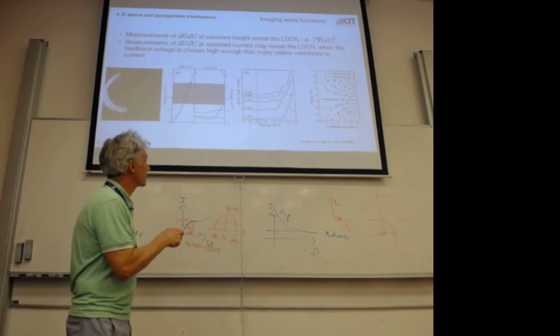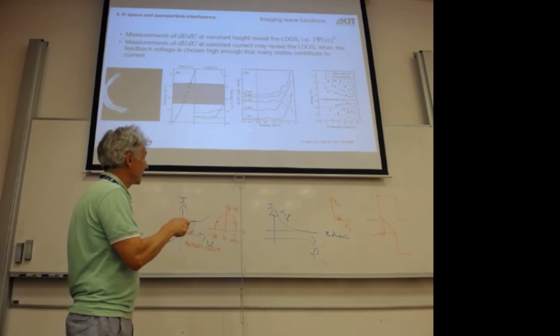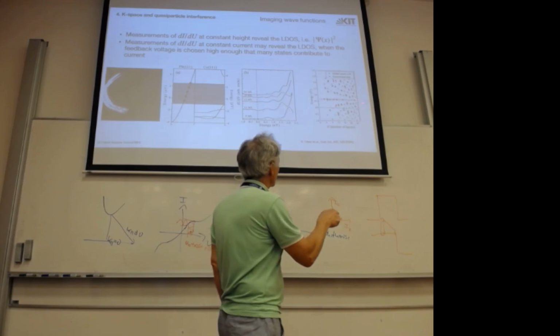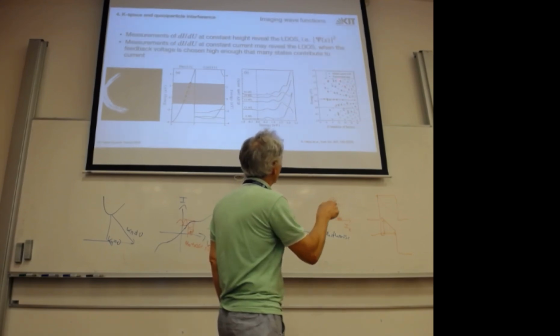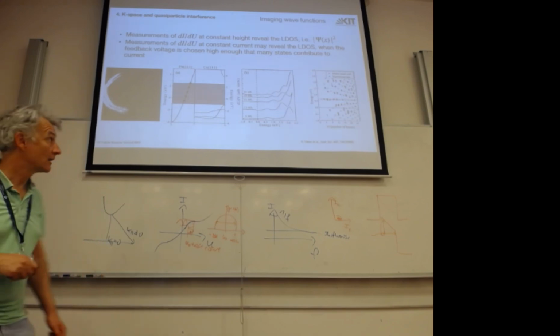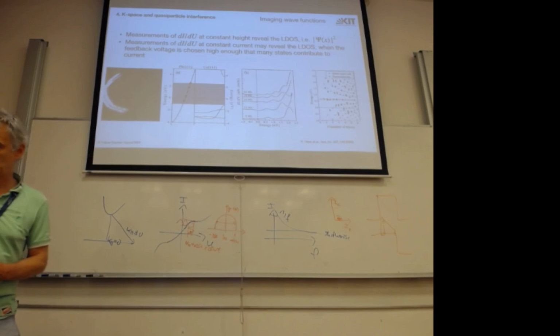And exactly this you can see, depending on the thickness of these layers, you can see these quantum well states. And if you just take this band structure, these are the dots, experimental ones black, infinite square well is open symbols, they agree pretty well with these peaks. So these are quantum well states confined in the z direction.